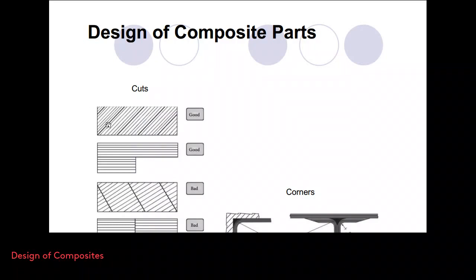So the first figure is the good placement of the fabric, and in fact, because we cut the shape and we orient the fabric in a manner that we don't shorten the fibers. So these are the direction of the fibers. So fibers are all along the part, and the dark black lines are the cuts. If you have an L-shaped geometry, of course this is the good placement of the fabric. Moreover, we can place the fabric like this.